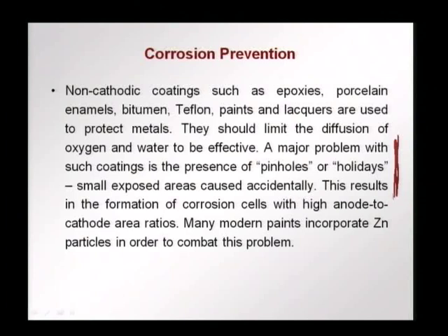One way to make this coating better is to have particles such as zinc in the paint that we use, so that if there is a pinhole or a holiday, the zinc will corrode rather than the base steel corroding.